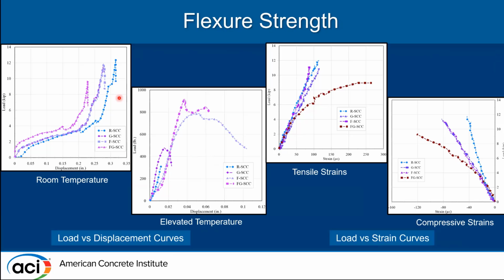Here I have just the graphs for load versus displacement curves at room and elevated temperature. Once again, these highlight the ductile behavior of mixes with hybrid fibers after fire exposure, where we can see that displacement is very much higher when compared to the mixes without hybrid fibers. However, at room temperature, like I explained, the failure was brittle for all the beams, and this ductile behavior only appeared after the fire exposure.